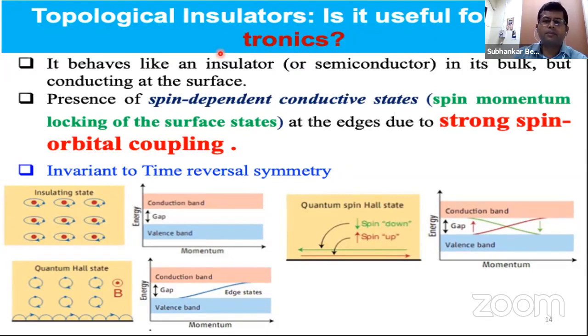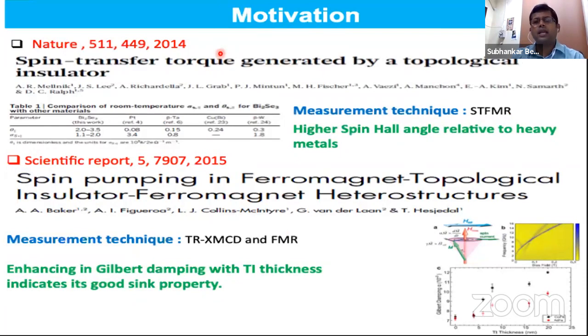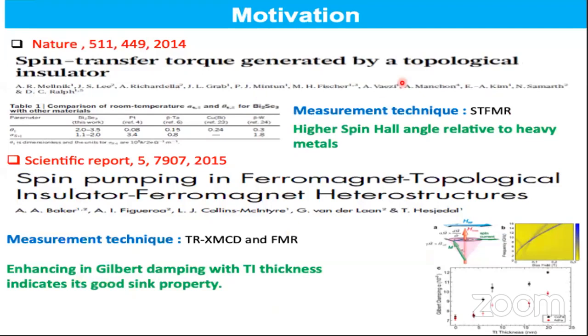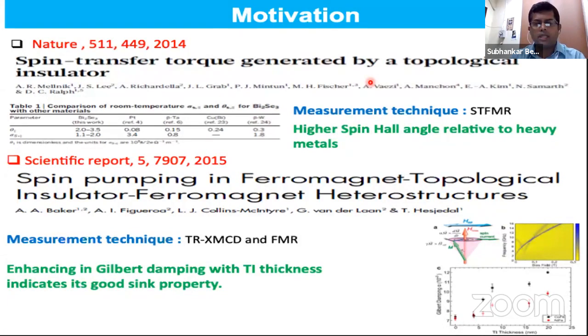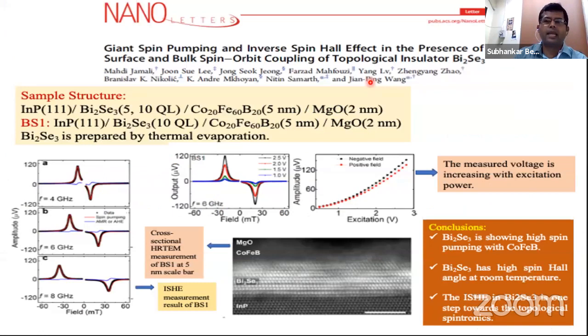And then the question is, if it exhibits a high amount of spin orbit coupling, then it can exhibit a high amount of spin pumping. There have already been some very nice reports, a breakthrough paper where they took bismuth selenide and did the STFMR, and they showed that spin pumping is possible. However, all these papers mostly have taken bismuth selenide prepared by molecular beam epitaxy, which is a much more involved and expensive technique. There have, of course, been some papers where people prepared bismuth selenide with thermal evaporation.